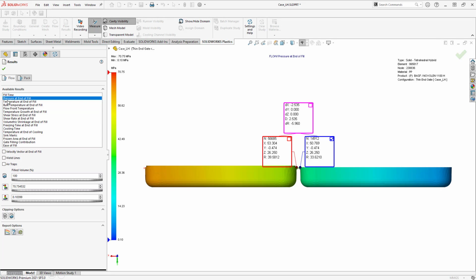Some of the other results we have: we were looking at the fill time plot to watch the flow and the pressure in the fill. I talked about the pressure drop between the two cavities. It's going to identify the pressure drop by looking at my pressure in the fill. We also want to make sure that with our pressure, we're not limiting out the injection molding machine. So in this case, my pressure is 70 megapascals. If my molding machine only had a 100 megapascal limit, I would be closer to the top of that limit. We want to make sure that we're not at that higher range.